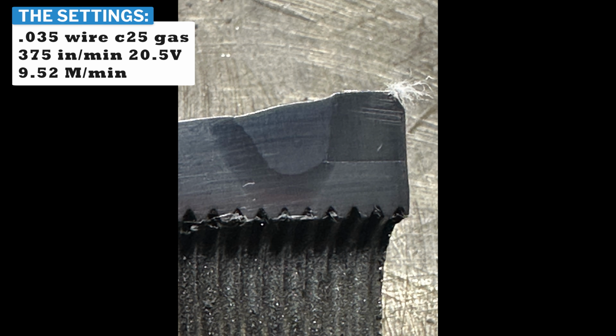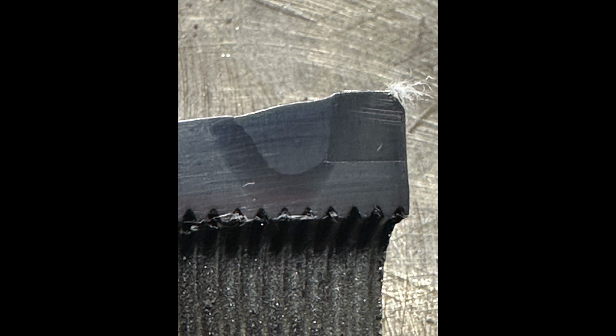So these settings worked out to be about 180 to 190 amps of output. So pretty decent, significant output here. And with that 035 wire again, which is what I used, the performance here is really good. And this is probably the best that we've seen, arguably. It got full fusion all the way in. It broke down the sides pretty decent, and it filled it all in a 1-pass, 1-deal shot.